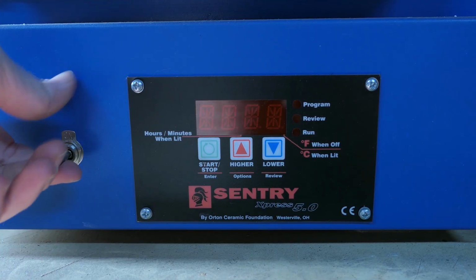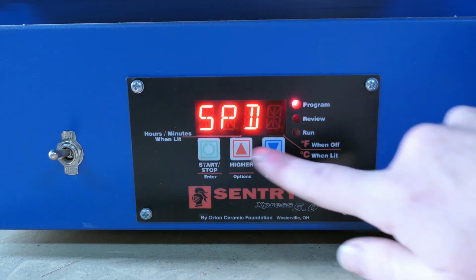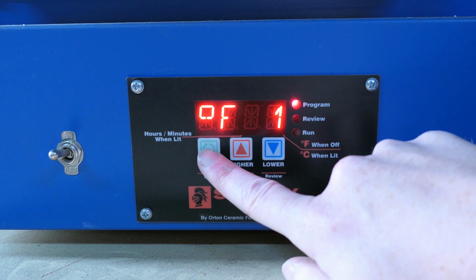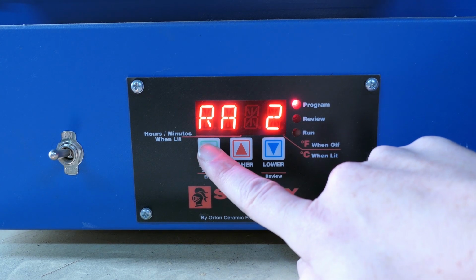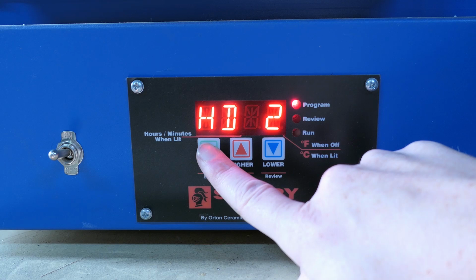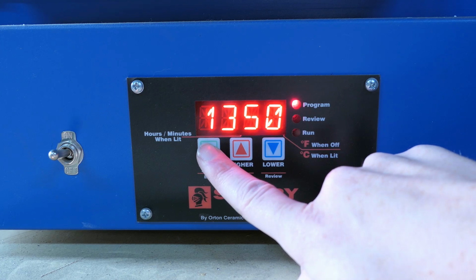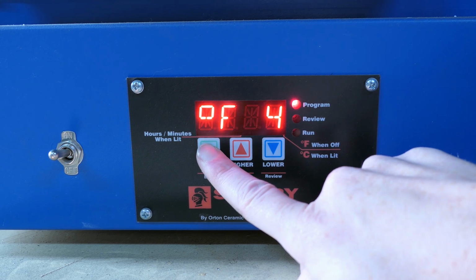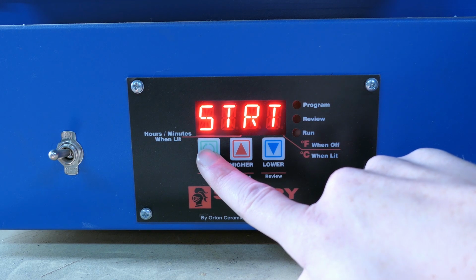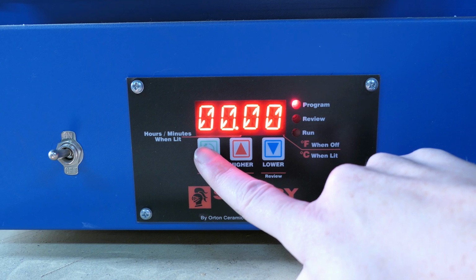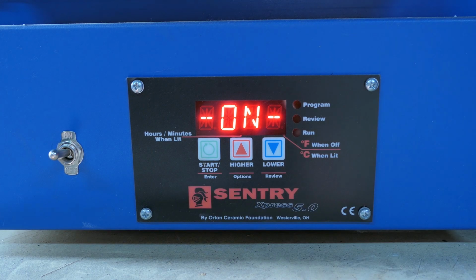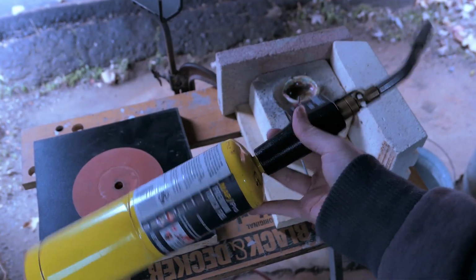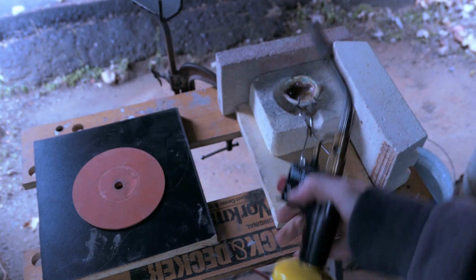And I'm going to be using a pretty standard burnout cycle, starting at 300 degrees Fahrenheit, then rising to 700, then topping out at 1350 degrees, until dropping back down to my casting temperature at 1000 degrees. And to melt the silver, I'm just going to be using some ordinary MAPP gas with a standard torch head.